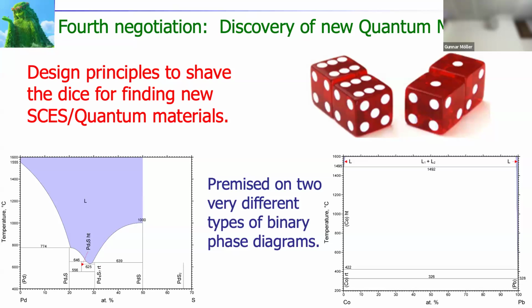Right. Now, is anyone not familiar with how to read a binary phase diagram? Okay, good. Let's have a quick primer. All right. Temperature, composition, pure palladium, 70% sulfur. Okay. This is a single phase region. It's a liquid. Okay. If I cool down and hit this, I'm entering into a two-phase region. I'm starting to get a solid, in this case, solid palladium, and this defines the composition of the remaining liquid.